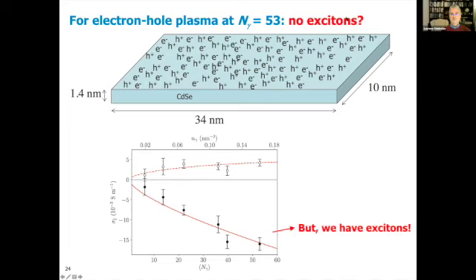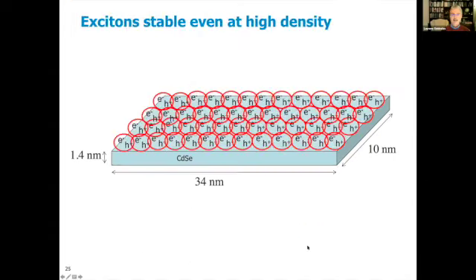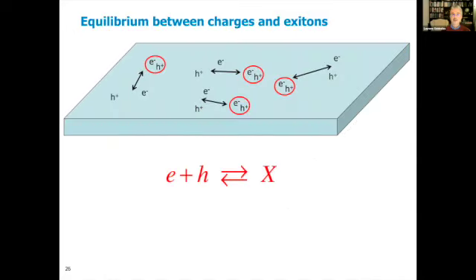So you could expect that you had no excitons, that you had this transition to an electron-hole plasma, but according to these terahertz conductivity measurements, we have excitons. And the excitons are apparently stable even at a high density when they are sitting, let's say, in contact with each other. And now we started theoretically looking at the equilibrium between free charges and excitons.